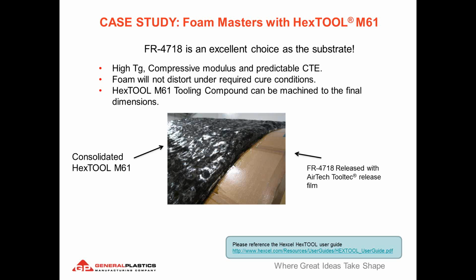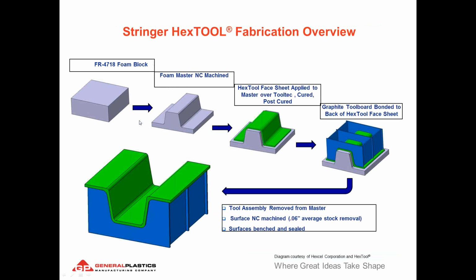This is a photo of a consolidated but uncured HexTool with 4718 released with Airtech release film. And these photos and a lot of the process are taken right out of the HexTool user guide we've referenced below. So the overall process we're going to run through is looking at a 4718 billet, machine it down to its desired shape, we seal it, lay it up, cure it, post-cure it, and then we demold the product and build up a backing structure, and that will give you your finished tool. And we're going to focus more on these two steps in the middle here.